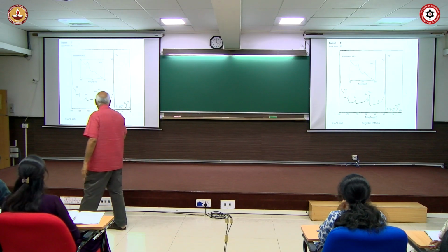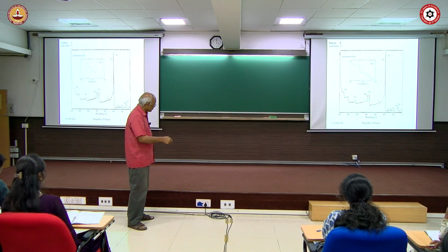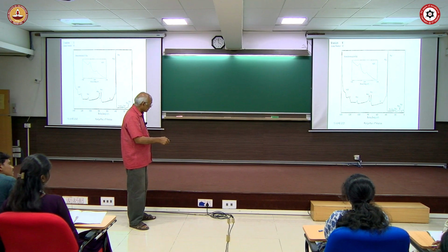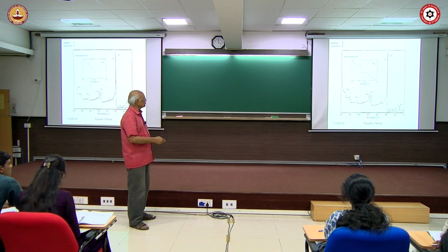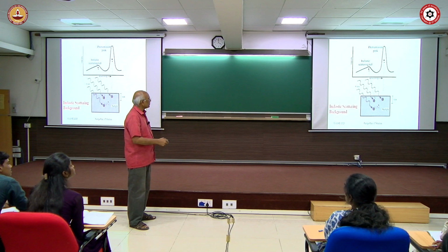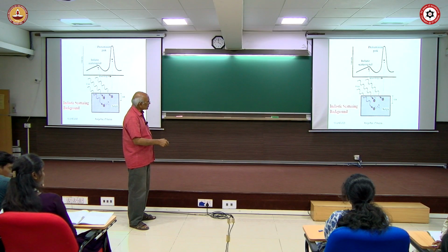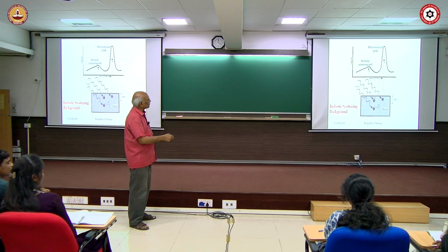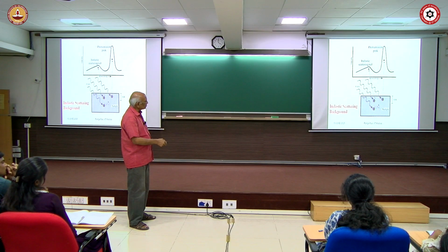Now let us look at why we have these two peaks here. We should get only one peak, but there is something here, some numbers also. What are those numbers, what is it due to? Since I said there are only about 100 angstroms, that is the region from where you get the original spectrum. Whatever is coming from inside loses energy, and that forms an inelastic scattering tail.